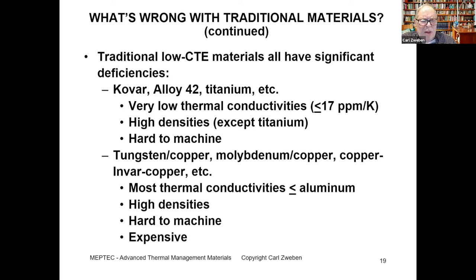We have other low expansion materials, copper tungsten, copper moly. Those are actually metal composites rather than alloys because there's no dissolving of the molybdenum in the copper or vice versa. And then we have copper invar copper, which is a laminate. So they have thermal conductivities pretty much less than or equal to aluminum. They have high densities, they're hard to machine, and most of them are expensive.